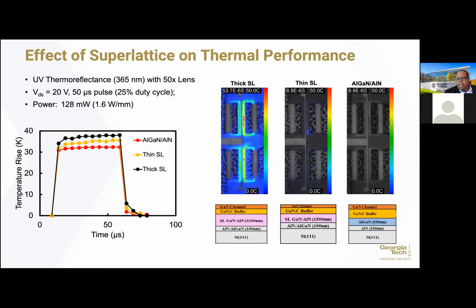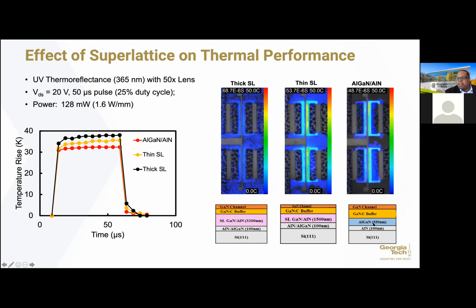So here's the first one. I have a thick superlattice structure. I thin this by about a factor of 2, not quite. You can see, qualitatively, the temperature is going down. And now I have this AlGaN structure, again this highly tensile version, and you can see the temperature is the lowest. This is exactly what we'd expect: the thick superlattice structure versus thin superlattice structure versus no superlattice structure. The temperature is dropping. This still doesn't help me in terms of fielding these devices with the superlattice structure while cooling them. So the technique here, in order to introduce some heat spreading, is this: since the stresses are controlled by having the superlattice structure, can we grow a much thicker layer of GaN, which I can't do in the other device, to actually enact heat spreading?